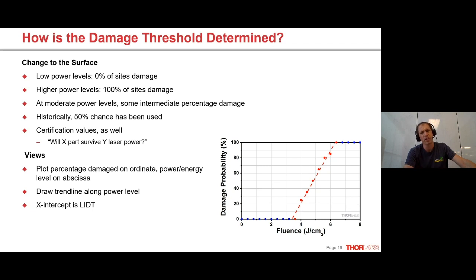You don't necessarily have to hit 100%. Obviously, a general upward trend is useful. I can't tell if what you're describing is a relatively random pattern, like you see damage at 1 joule per centimeter squared, and then no damage at 2, and then damage at 3, and then no damage at 4, then I would say you would probably want to look at your process. You probably need to do a better job of keeping things clean. But typically, even if you don't get to 100%, you would eventually see an upward trend.